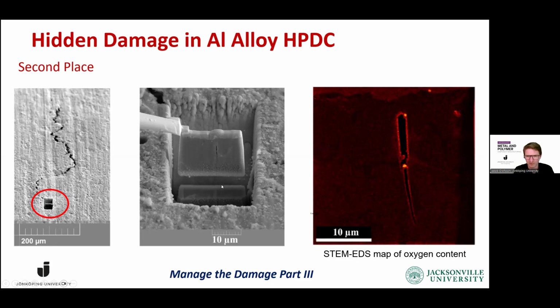And looking at the map of the oxygen content here, we can see that this is clearly an oxide that has also been causing this crack that ends up now in second place. So it didn't cause the fracture, but still it caused a crack. And there was a competition going on between this crack, which is actually much higher up on the sample. So it's not subjected to the same load as the central area, but still the material has been cracking here.